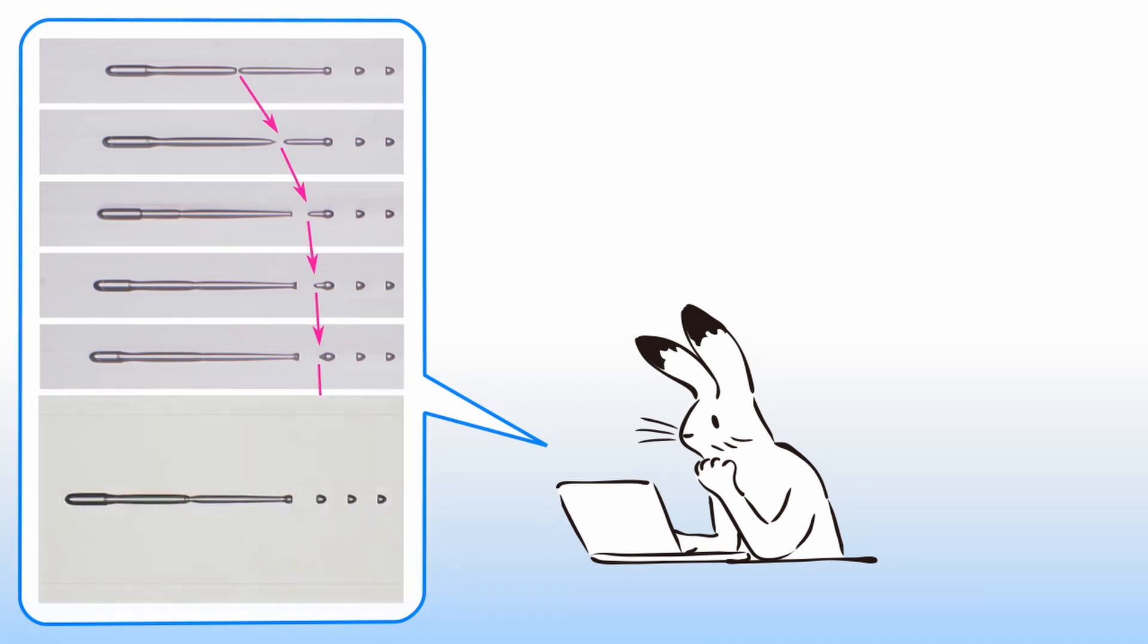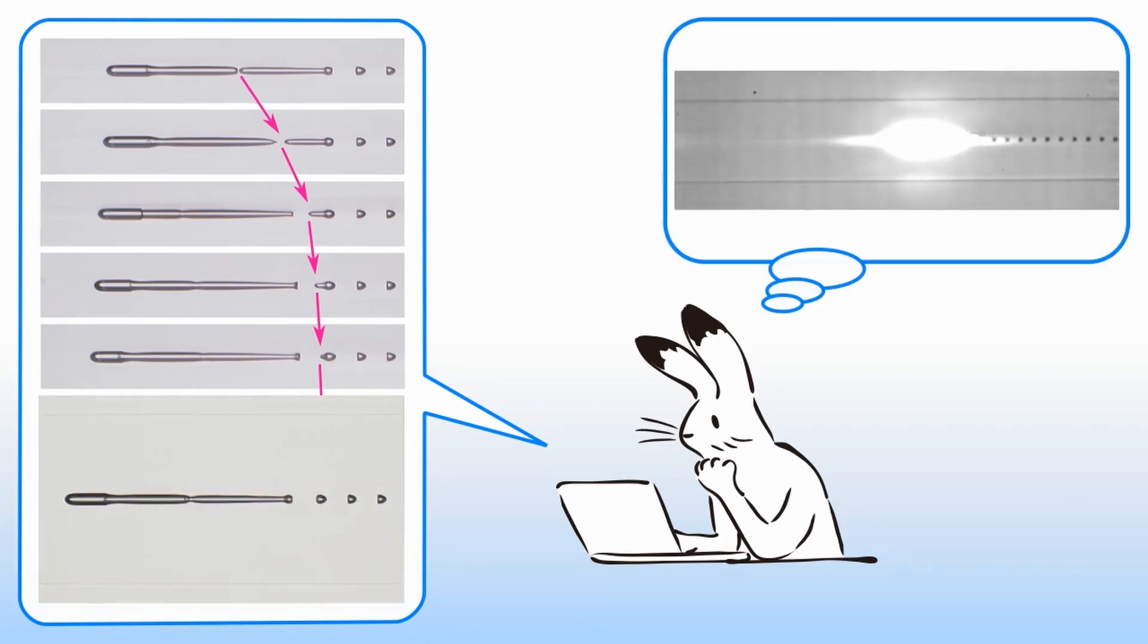We have to notice, however, that these photographs show the structure of cooled glass after the shutdown of laser beam. So, it is not a direct observation of fiber fuse propagation at elevated temperature under high pressure. But, it is reasonable to consider that this sequence retains a hint of the void formation cycle veiled in the strong light emission.